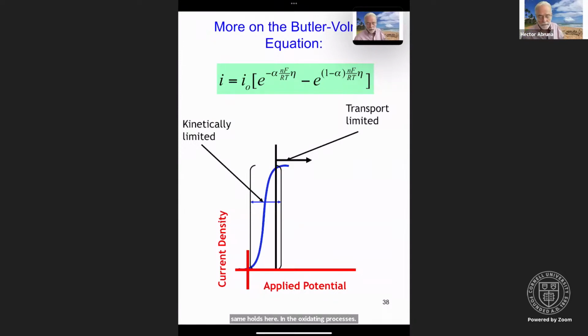A bit more on Butler-Volmer. If we look at current density as a function of applied potential, in the interval where the current is potential dependent, this so-called kinetically limited regime, you can see that the current is dependent on the applied potential. Eventually, it will reach a mass transport limit. So it's no longer kinetically controlled, meaning you have applied a large enough overpotential to overcome any and every kinetic barrier.